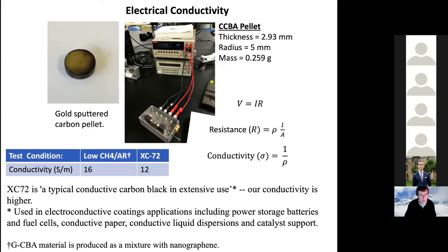And we have compared that mixed material, nanographene plus the conductive carbon black analog, to XC72. The way we have measured the electrical conductivity, shown in the upper panels, is that we made pellets of the material, sputtered gold for electrical contact, measured the resistance, and calculated the conductivity. Relative to XC72, another well-known commercial conductive carbon black used as an additive for batteries and capacitors, electrodes, the mixed material actually has a superior electrical conductivity.